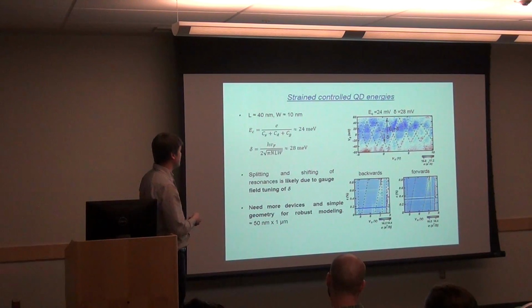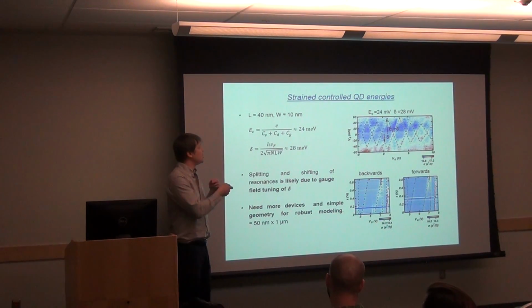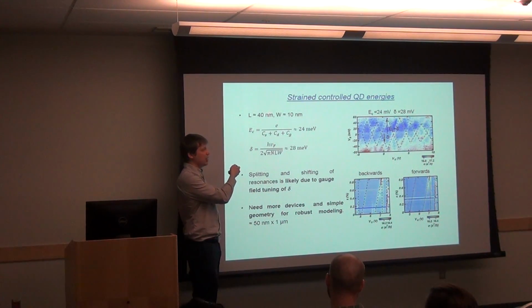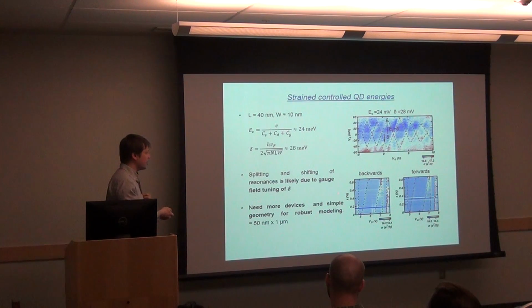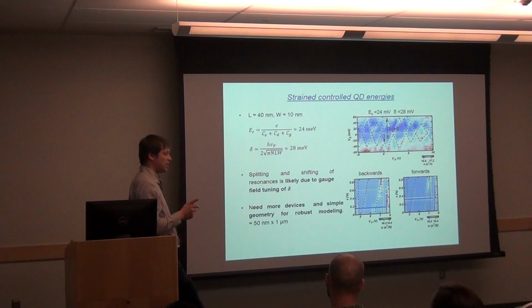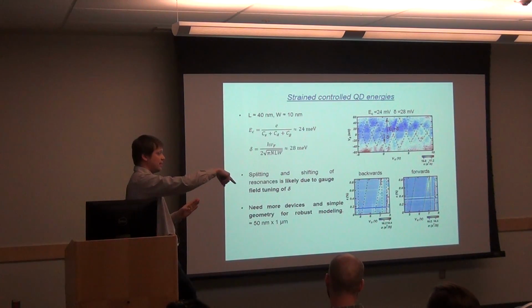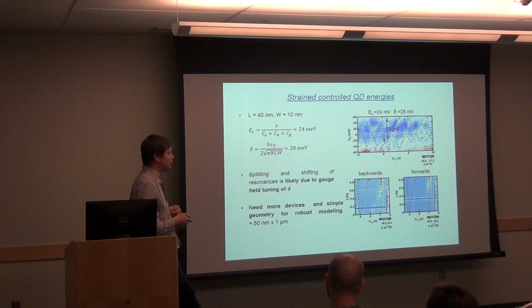So if you have a device, in this case, we used the electromigration procedure. So the width was only about 10 nanometer and the length 40 nanometer. So those make quantum dots. And we saw that the energy levels in the quantum dots could be manipulated with strain. This we don't fully understand, but the idea is that the energy level in a graphene quantum dot depends on the path of the electrons. It depends how far the electron travels before it exits the dot. And if you change the angle of the injection, the length of the path to exiting the dot changes. So that's something we'd like to be able to model theoretically. We have some ideas, but it's not there. But the fact it's fully reproducible going forward and backward, we can split some levels and merge some levels, and it looks a lot like, for example, some of the degeneracies that are in the Hamiltonian.